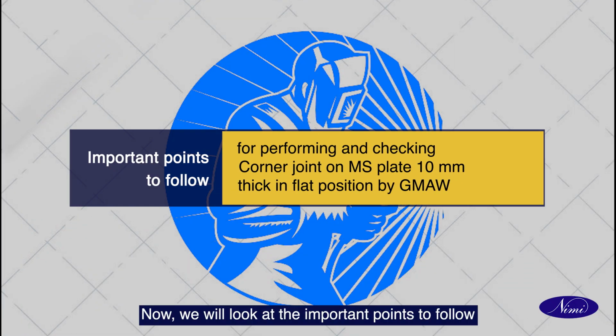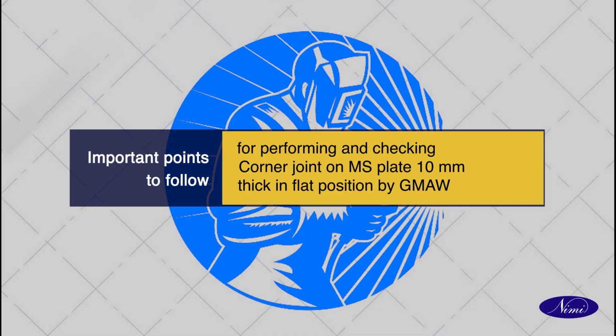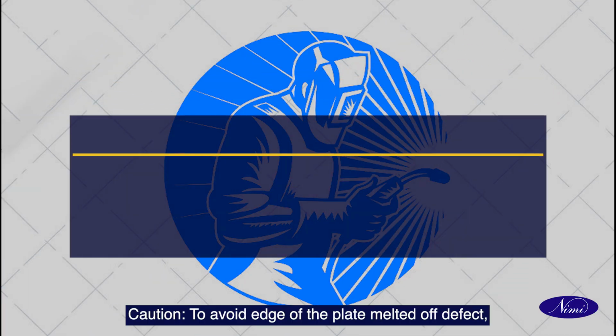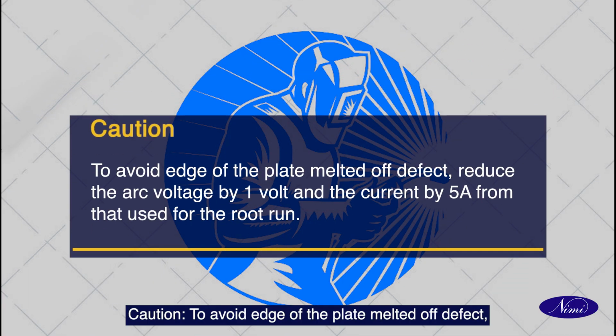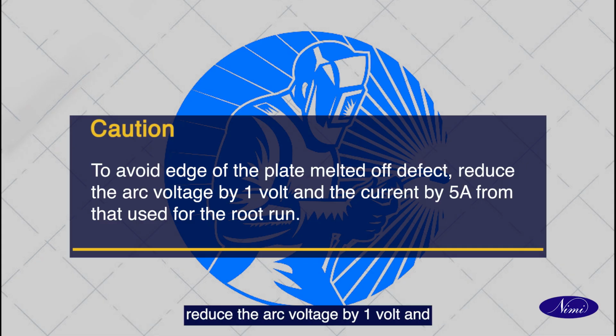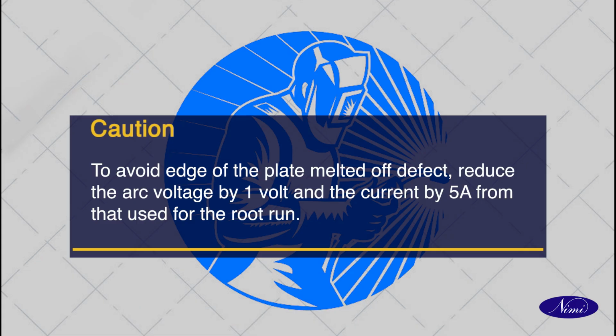Now we will look at the important points to follow for performing and checking corner joint on mild steel MS plate 10 mm thick in flat position by GMAW process. Caution: to avoid edge of the plate melted off defect, reduce the arc voltage by 1 volt and the current by 5A from that used for the root run.